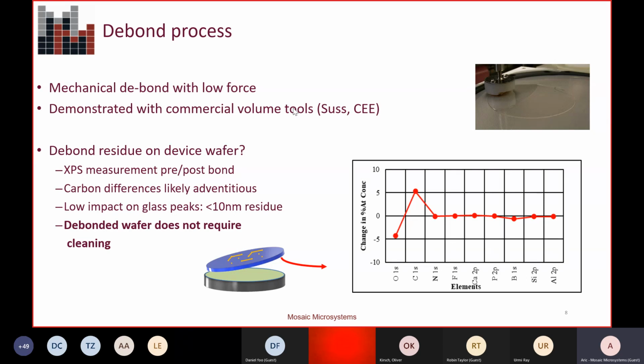Another important aspect, so a lot of people wonder what's the surface of the glass after debond. And so what we did is we took a couple of wafers or a couple of process sets, 2 different cleaning processes, and so the wafers were cleaned, and then one surface was bonded to each wafer. And then we debonded it and did an XPS of each surface. So the intent is, the top surface that didn't touch the handle wafer is sort of an as cleaned surface. And then the debonded wafer would be, if there was any contamination, the contamination from the bond layer.